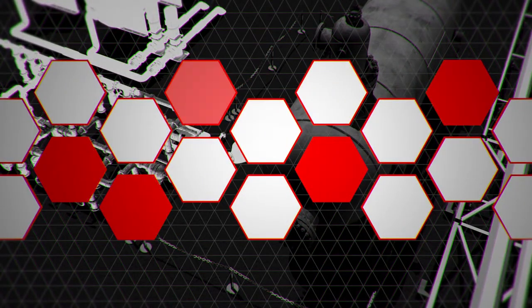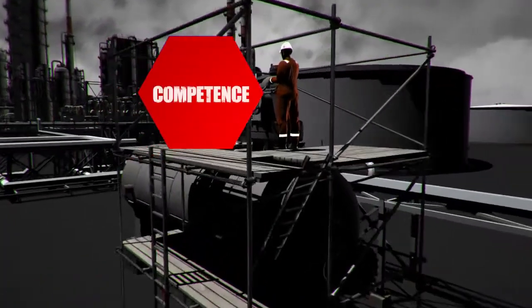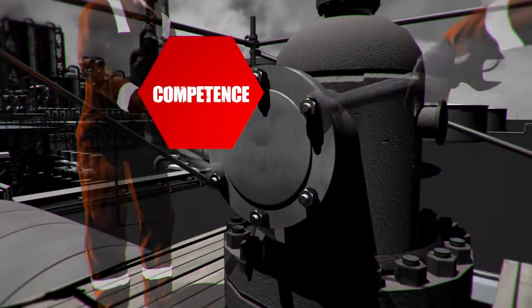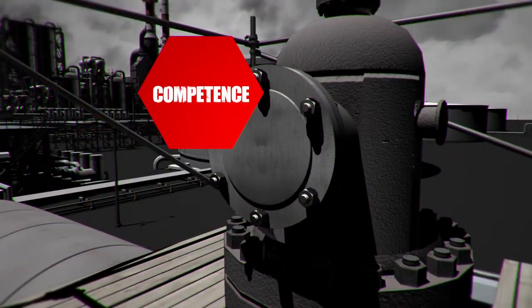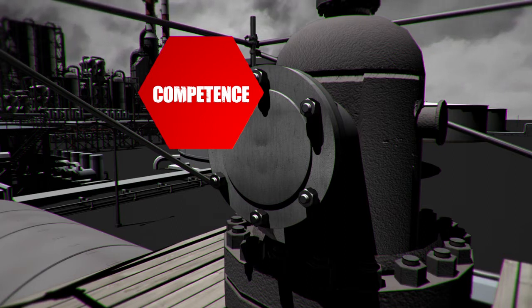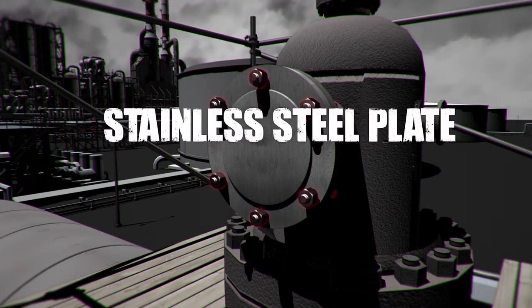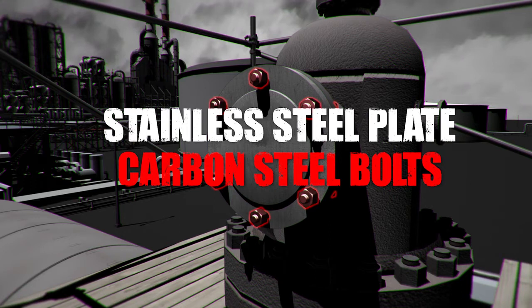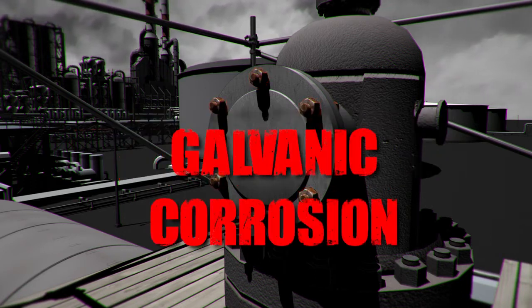Several barriers could have prevented this incident happening. Let's look at just some of the barriers that failed. 1. There was a lack of competence in both procurement and the maintenance team when the blank flange was installed on the bulk storage tank. A stainless steel plate had been fitted with carbon steel bolts, causing galvanic corrosion over several years.